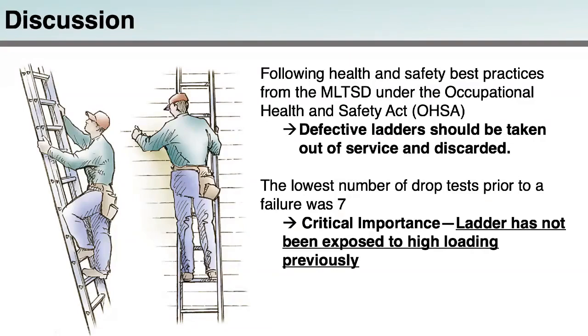Lastly, in terms of the aluminum ladders that we tested, the lowest number of drops prior to a failure was 7. So we did have one, the middle ladder that we tested, that only survived 7 different drops. So this emphasizes the critical importance that results from this investigation are based on a ladder that has not been exposed to any high level loading or damage event previously.